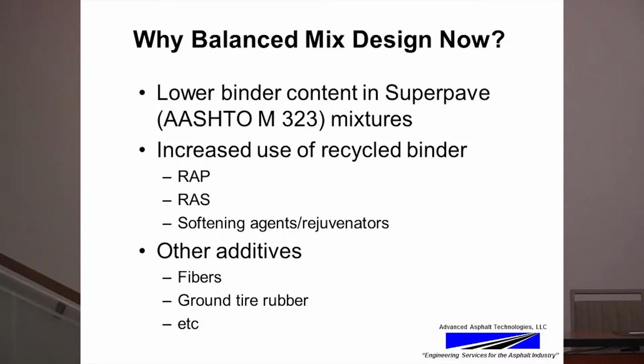Some of the things we've been seeing over time, within the Superpave design system, AASHTO M323, are mixtures that have a tendency to have lower binder contents than what we've seen with, let's say, Marshall mix designs in the past. This lower binder content, the lower volume of effective binder in a mixture, tends to produce mixtures that are more susceptible to cracking and durability problems.